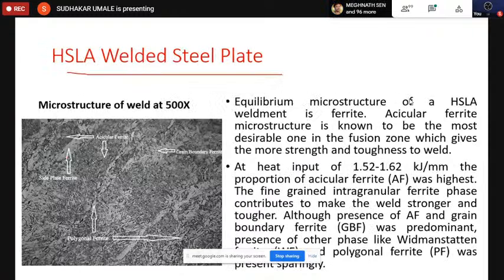Now this is a welded steel plate. After welding, this is the plate material I got. Just observe, I have the acicular ferrite structure. Here is acicular ferrite. This is grain boundary ferrite. This is side plate ferrite. This is polygonal ferrite. And you observe that I have got the maximum patches of acicular ferrite in the welded joint. Therefore I have selected this as my input for getting the maximum acicular ferrite, that is 1.52 to 1.62.